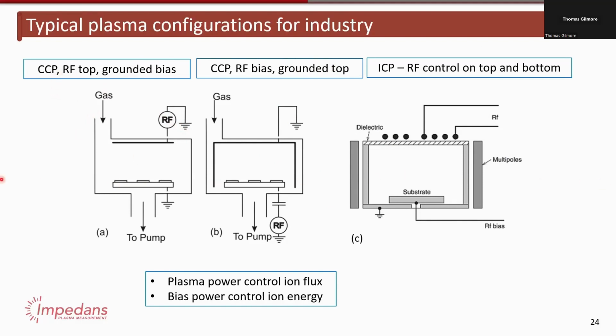Here's some typical chamber design. You can change where you apply the power. If you apply power only to the top electrode and you have nothing on the bottom, you're effectively just going to change the plasma density and slightly change the plasma potential. I'll show you some real data in a moment, but this is one way of increasing or decreasing deposition rate, just by playing with the power on the top.